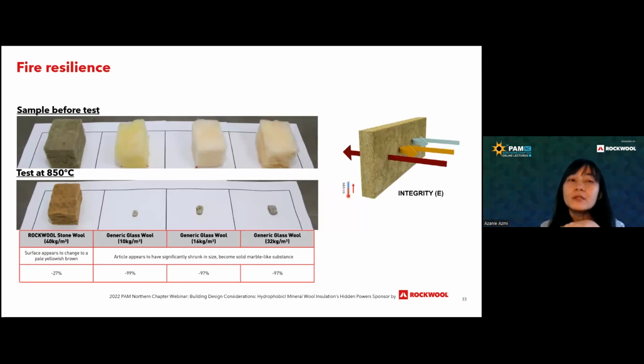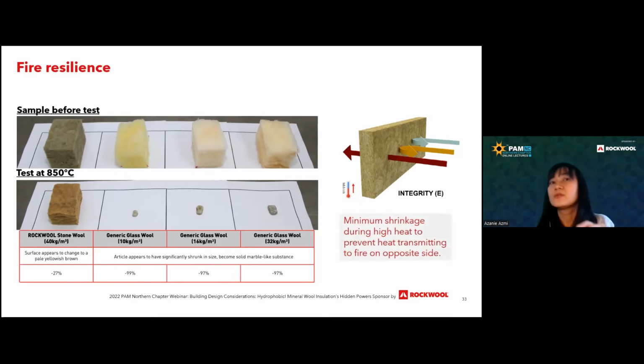What we do here, we put the sample in the oven at 850 degrees C, and then we check the volume. We see that Glasswool totally shrunk around 97 to 99%, whereas Stonewool only reduced around 30%. So what I mentioned previously, you have minimum shrinkage. You have high melting temperature, very low shrinkage, and when there's heat, it's able to prevent the heat transmitting to the fire on the opposite side.